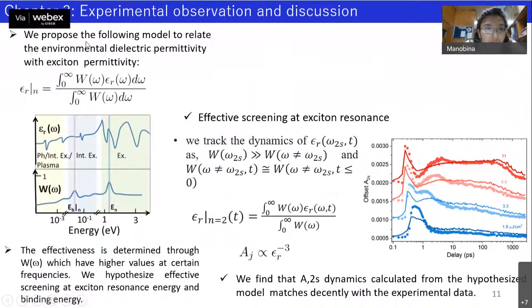Now we propose the following model to relate the environmental dielectric permittivity, which is a function of frequency, with this effective permittivity, which is just a number. So with this model, we put some additional constraints, like some assumptions that the screening is effective at the resonance. So here we are looking at the 2S exciton, which is the first excited exciton. With this assumption, we reproduce the absorption oscillator strength enhancement of the 2S excitonic state.